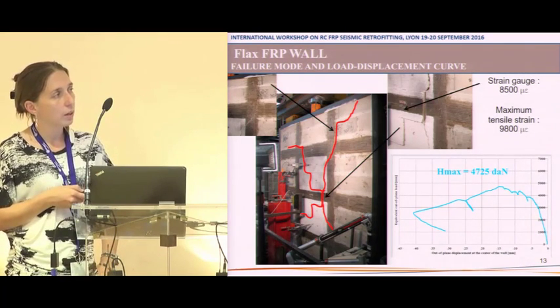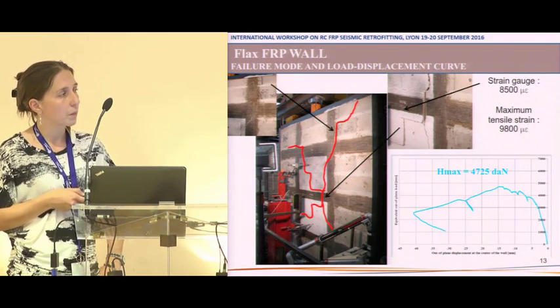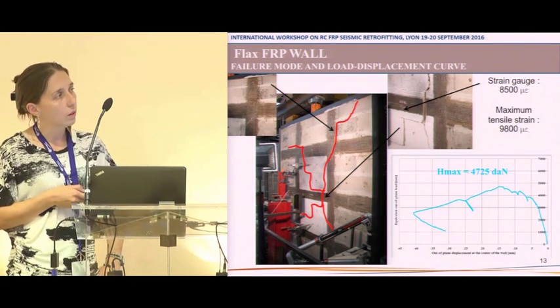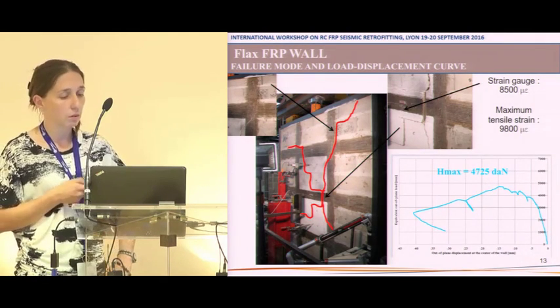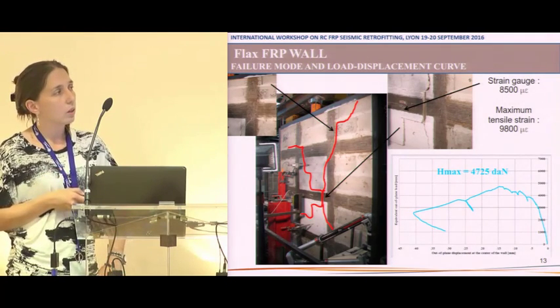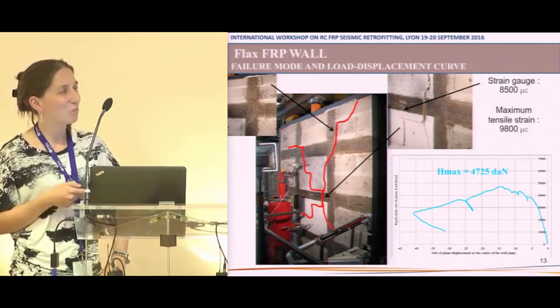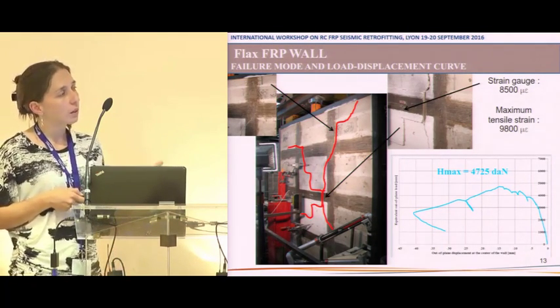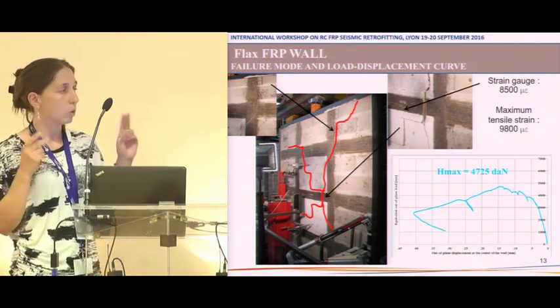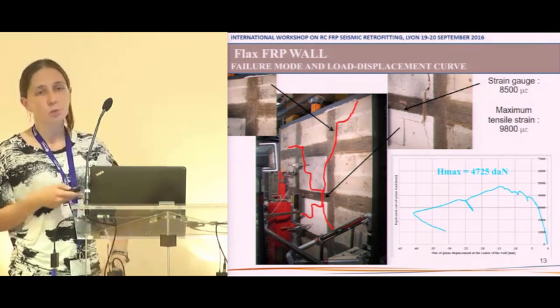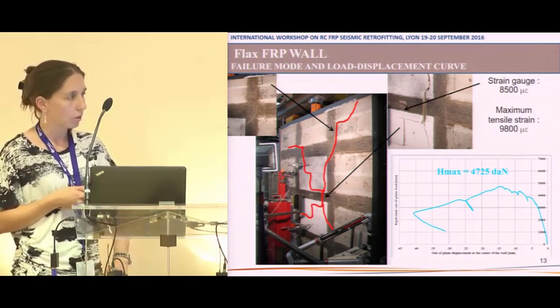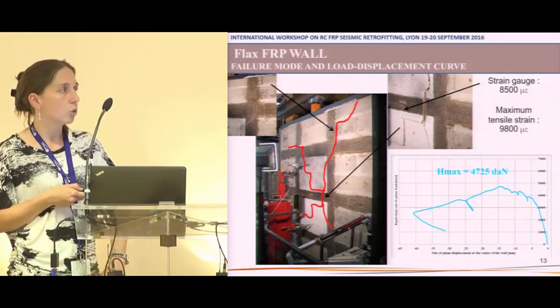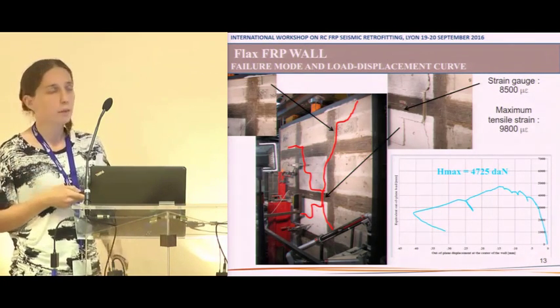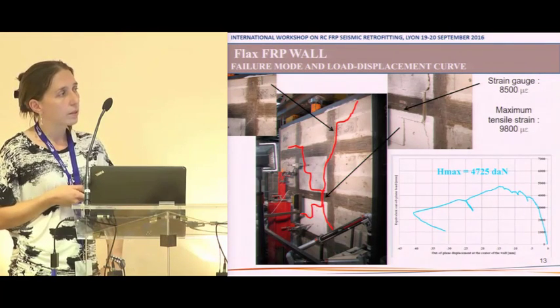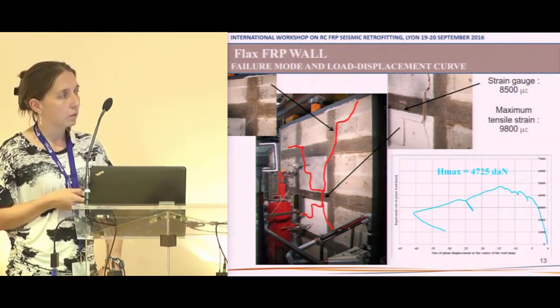In that case we have a failure at the central horizontal band of the FRP, and if we look at a strain gauge glued there, we can see that we reach 8,500 microstrains. That is to say, we are at 90% of the ultimate tensile strength. So this shows that the stress redistribution is not really optimized with such a material, and that our anchorage systems may be efficient in the present case. We have an increase in the maximum load, and a good ductility.